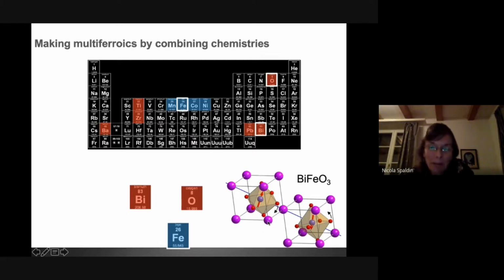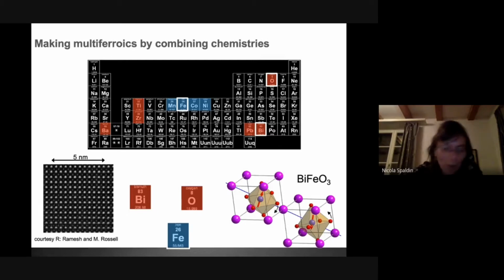And bismuth ferrite actually already existed. It had been worked on already in the 1980s. And again, we were successful with bismuth ferrite, not because we had a better idea than people who tried it before, but because we had better samples. Because of modern thin film growth techniques, it turns out bismuth ferrite is not so easy to make in a good quality sample.